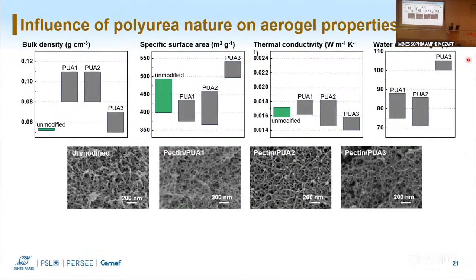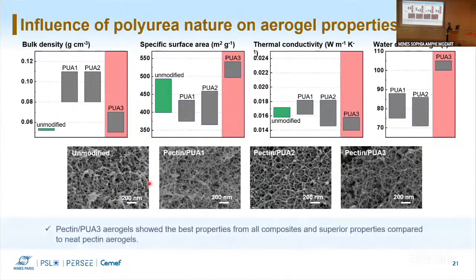Looking at the structure of our material, we cannot really see a difference. So the first picture is the neat material, and then there are the other composites with similar concentrations. And we cannot see a secondary network or any particulate form. So we suppose that we have a nice coating around our pectin fibrils. Overall, we concluded that the third type of polyurea worked the best, so we decided to go with it. And also, we tested the aging and we saw that it had better stability in moisture.